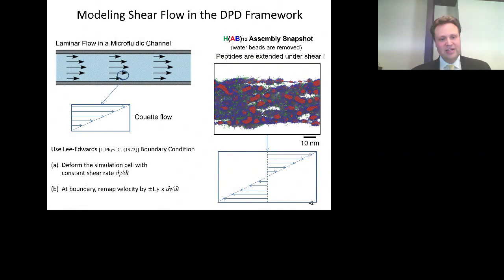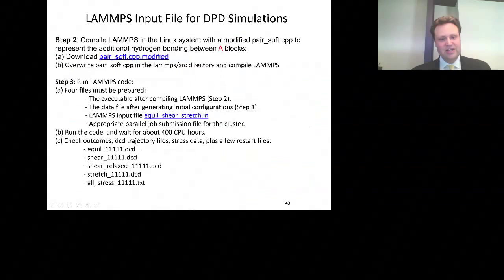Now, I'll show some data later that the simulation has confirmed. We've been able to essentially simulate the shearing using these Lees-Edwards boundary conditions. There's an early paper where this has been used for molecular simulations. We've adapted this now to the DPD framework, the dissipative particle dynamics framework, and we can control the shear rate during the simulation and simulate the shearing process.